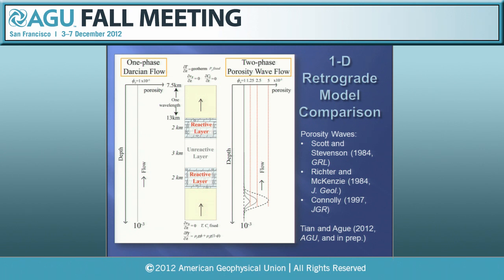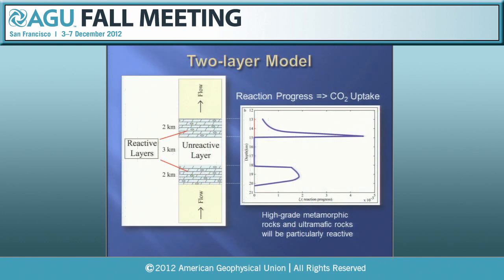The good news from the standpoint of just simplifying chemistry is that whether it's a 1-phase or a 2-phase flow, Meng's calculations show that the reaction progress is basically the same for either case. So that simplifies our lives quite a bit. And to make a long story short, without getting into all the equations, here's what you see. Over on the right is depth, and we've chosen the depth so we're going from mid-deep crust up to the brittle ductile transition.